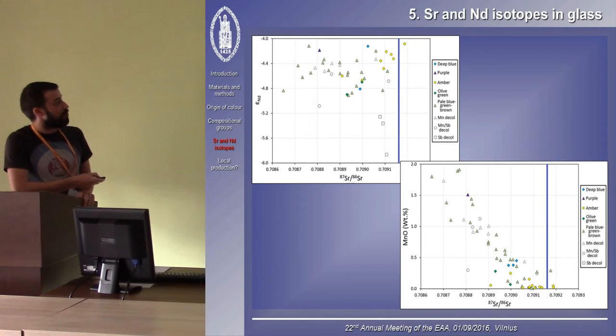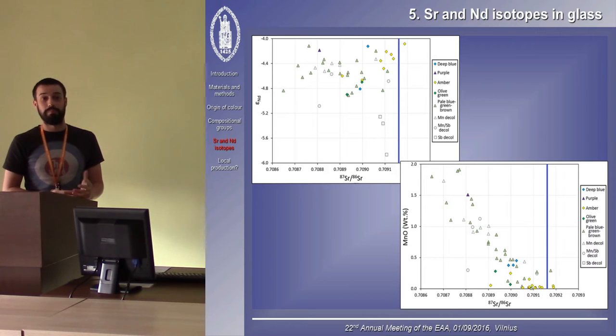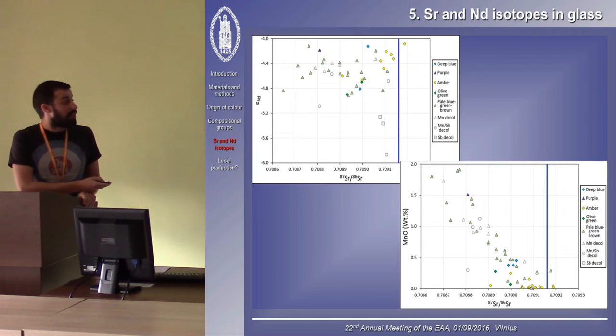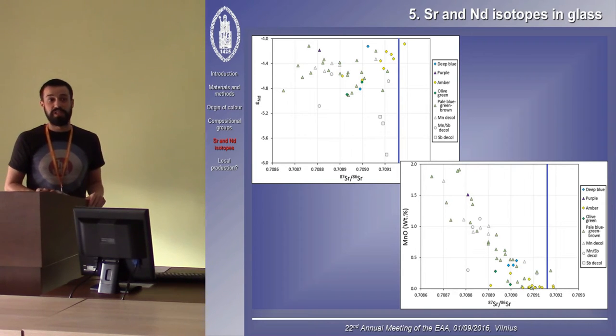Here we see the strontium isotopic signature plotted against the concentration of manganese in the glasses. For glasses which contain hardly any manganese, the strontium isotopic signature is actually very close to that of the modern-day seawater. Glasses with a lot of manganese have very low, much lower, isotopic ratios. There's a clear inverse correlation between the two. This suggests or indicates that the manganese-bearing ore, or the manganese-bearing minerals, that were added to the glass to make the glass colorless, actually brought in quite a lot of strontium with relatively low, non-radiogenic, isotopic signatures. The strontium isotopic ratios in the pristine glass, so before being decolored, would have been very close to the seawater value, and hence would again indicate the use of beach sand for their production.